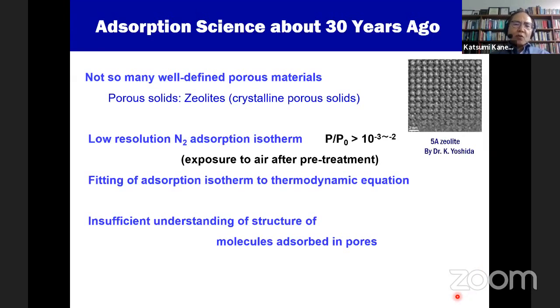Ordinarily, the adsorption mechanism depends on the surface structure. The BET theory applies to a flat surface, but around 30 years ago, although there were so many excellent scientists at that time and very nice science was published, there were still some limitations, with not so many well-defined porous materials. One of the well-defined porous materials was zeolites. Others are not so well-defined.